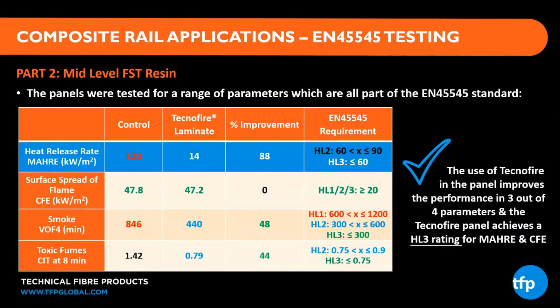If we now look at the results from the mid-level FST resin, and this is exactly the same structure of the table. So we've got the heat release, the surface spread of flame, the smoke and the toxicity. If we look at the control, we've got a significantly better heat release rate compared to the orthophthalic resin in the last table. The ortho gave 300. Here we're down at 120. So as you'd expect, this is an FST performance resin, so we're going to see a lower heat release rate. But if you look at the impact of incorporating the Tecnofire, we've improved that by 88% and have dropped the heat release rate down to 14.